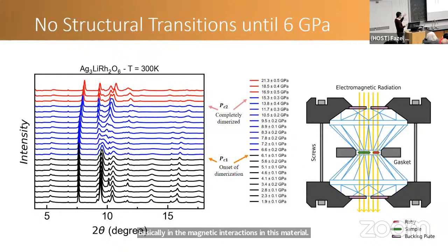Now, another thing that we wanted to check was that there is no structural transition under pressure, such that this suppression of magnetic transition is only due to a shift of balance between different competing interactions, such as Kitaev and Heisenberg terms, not due to a structural transition. So we studied the X-rays under pressure, and we saw that there is no structural transition up to 6 GPa, but above that, you see there is a branching of X-ray peaks, and that branching is indeed a structural transition that happens at about 6 GPa.